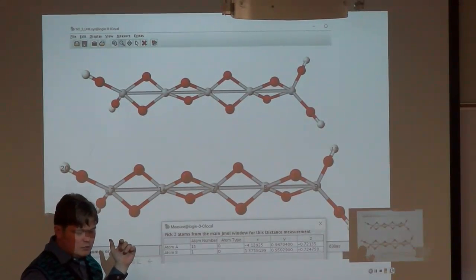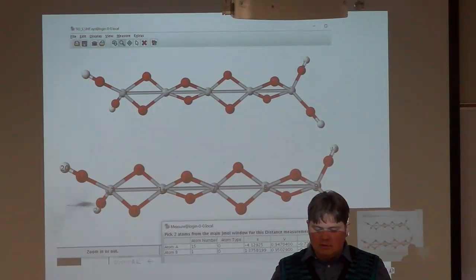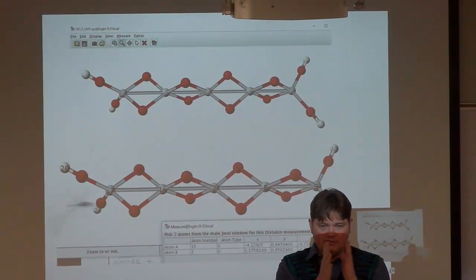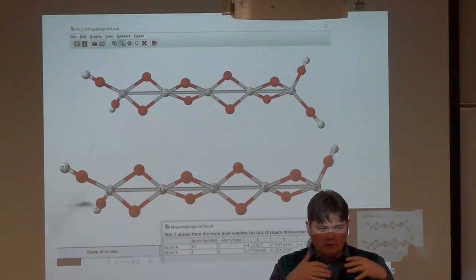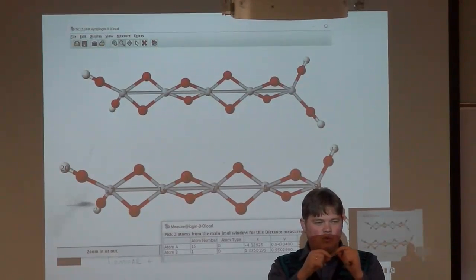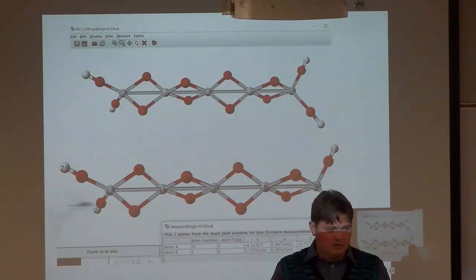But sometimes we want to be extra cautious and allow more than 1 unit cell. For which purpose? If you want to catch some additional normal modes, if you let it oscillate. Because if you have a smaller unit cell, the electronic properties will be fine, but if you need later to connect them to molecular vibrations, there will be less chance. If you have one unit cell, it will be only one mode. If you have a larger cell, it will have more chances to perform collective oscillations.